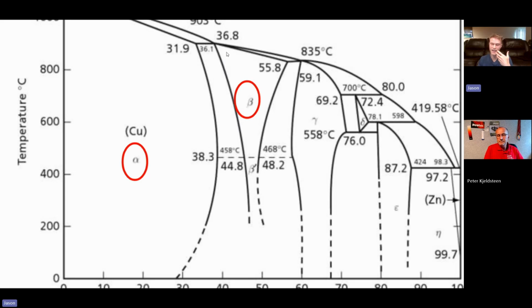I could have an ingot full of solid beta phase. And then if I cool further, that beta is no longer going to be able to accommodate all the copper, just like taenite wasn't able to accommodate all the iron. And so that copper will start to precipitate out as alpha as we move into the beta-alpha coexistence region. And if we cool slow enough, we may see some symmetry in the way that alpha forms. That alpha may grow in preferential growth directions, just like the kamacite rods that we see in Widmanstätten.